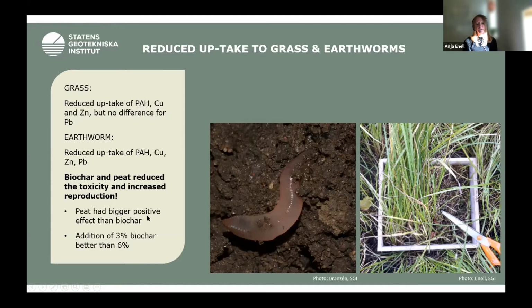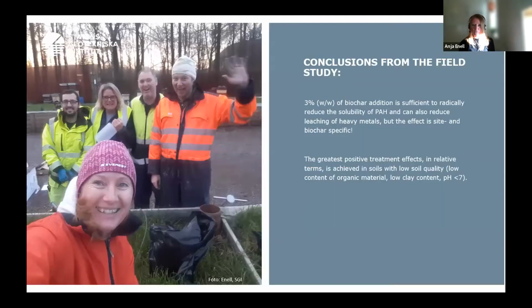I should say also that the peat had a bigger positive effect than the biochar. And we also saw that it was better to add just 3% of the biochar compared to 6% of the biochar in terms of reproduction.